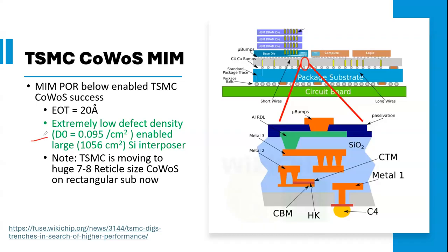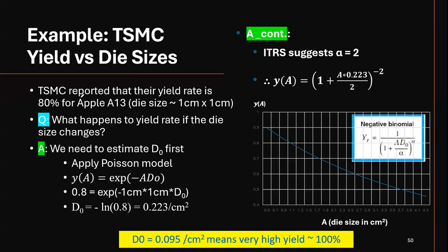The reason I keep emphasizing the yield is because that's what differentiates TSMC against Samsung and Intel. And look at that, why I said this is extremely good value. I use examples. I calculated that TSMC reported a yield rate of about 80%. This is just hypothetical. It should be higher, maybe 90%, but let's assume 80% for the Apple A13 data. For Apple 13, the die size is about 1 by 1 centimeter. So the question for you is, what happens to the yield rate if the die size changes?